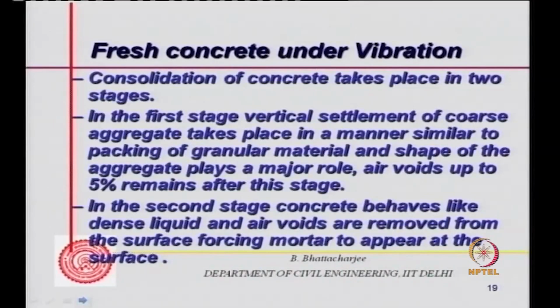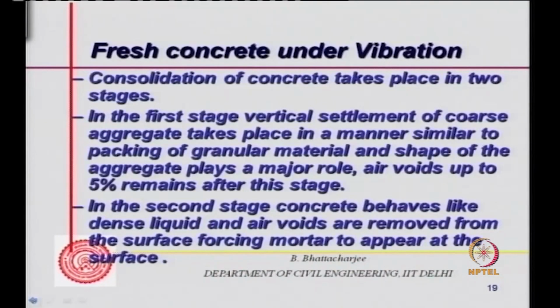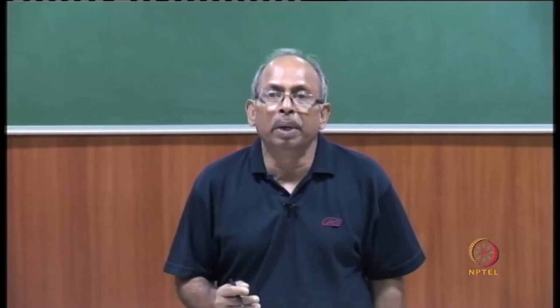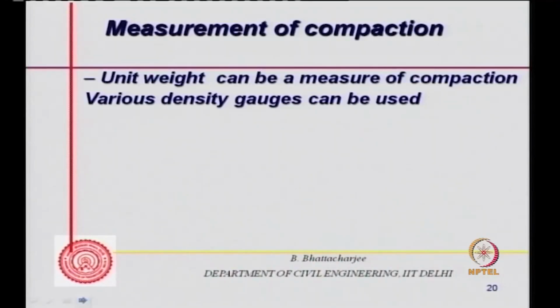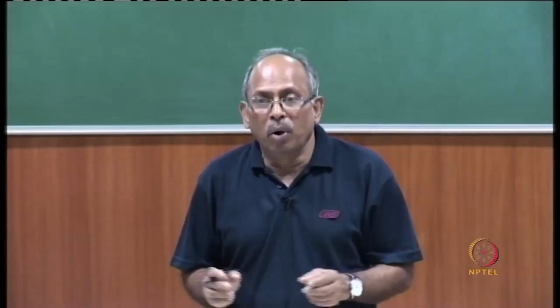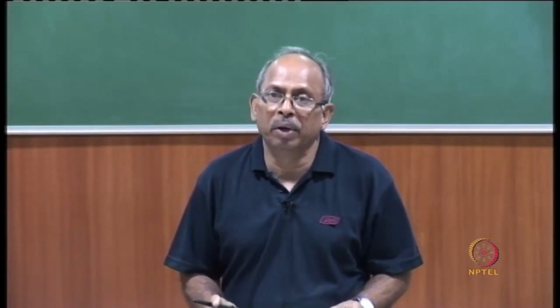Then, at the end of the second stage, concrete behaves like a dense liquid because the air voids have been removed quite a bit, and finally air voids are removed from the surface, forcing mortar to appear at the surface. So this is important to know: once the air voids move out, the mortar will appear at the surface. Once the first phase is over, in the second phase mortar will come out, and that's also a test for whether the vibration is complete or not. You'll find that a slurry or mortar phase is coming out at the top, and then you can stop vibration.